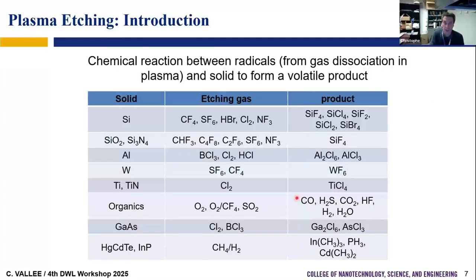For chemical etching, this is the first step we do when we do plasma etching. We need to understand what can be the volatile byproduct. Depending on what product can be volatile for a given solid material we want to etch, we have to select the gas we will use. If you want to make SiF4, you select a fluorine-containing gas. If you want to make SiCl4, you select a chlorine-containing gas, and so on. If you want to etch aluminum, aluminum fluoride is not volatile, so you etch with chlorine, for example, to make a volatile byproduct. If you want to etch a polymer, you use oxygen to form CO or CO2 and water, volatile byproducts. It's the first step for any plasma etching process: understand what can be volatile, so we can design the gas we use.